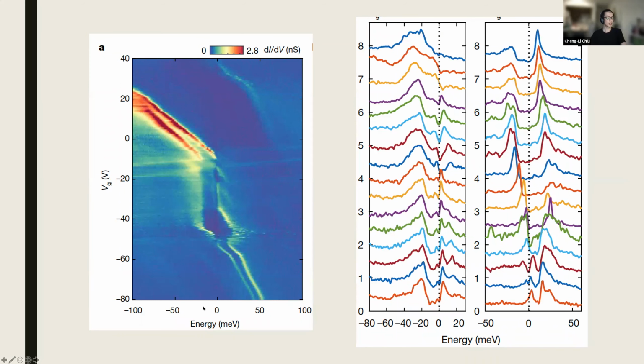And this is a spectrum taken at a lot of different gate voltages. In this axis is the density of states. Each line here, on the y-axis, is at a different gate voltage, and we plotted the intensity as different colors, so it can better visualize the evolution of the band structure. You can see when your flat band is far away from the Fermi level, they are like two independent flat bands. However, when you get close to the Fermi level, you see that it has a sudden change.